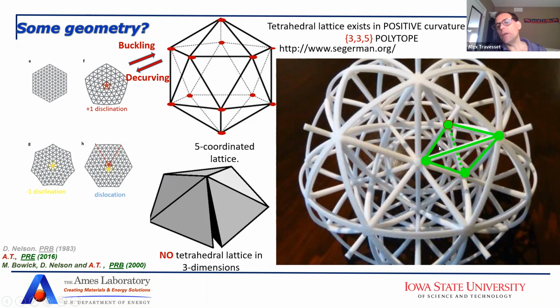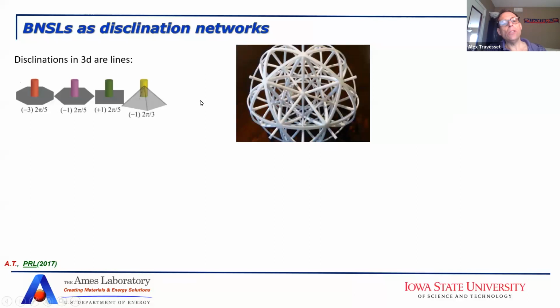So here you have to sacrifice something in order to be within 3-dimensional space, and you sacrifice the distances. But you can see that this structure is made of perfect tetrahedra that, if we were able to visualize in 4-dimensional space, would be perfect tetrahedra, all of them. So you will be able to tile this space by these things. The reason why I'm bringing this up is that in order to do the decurving, in order to go from this curved surface to a 3-dimensional space where we don't have curvature, you can do it through disclinations. And the disclinations that are allowed in this system, this is fixed by the symmetry group, are 2π/5 disclination and 2π/3 disclination with different charges.